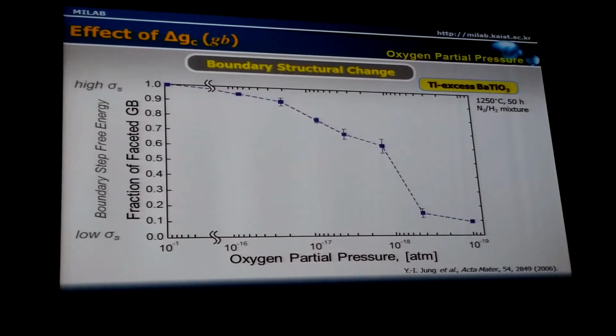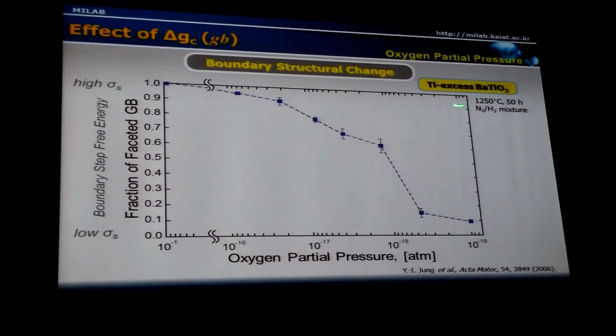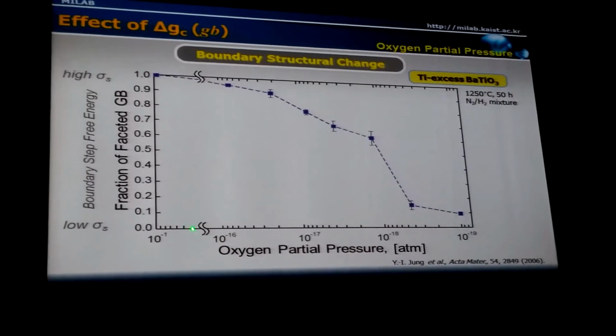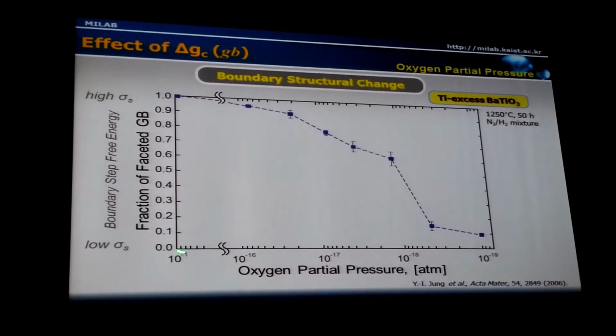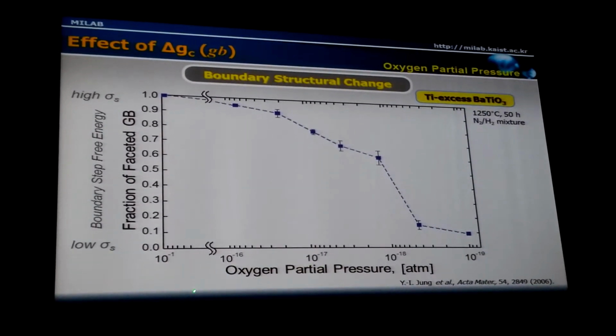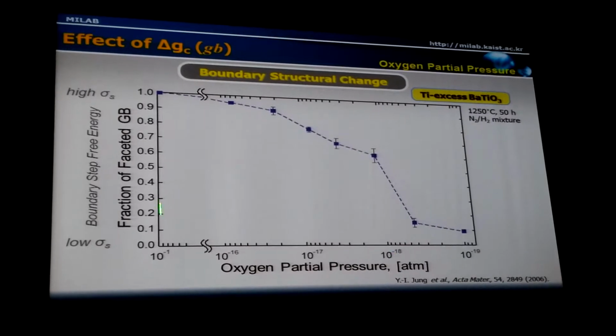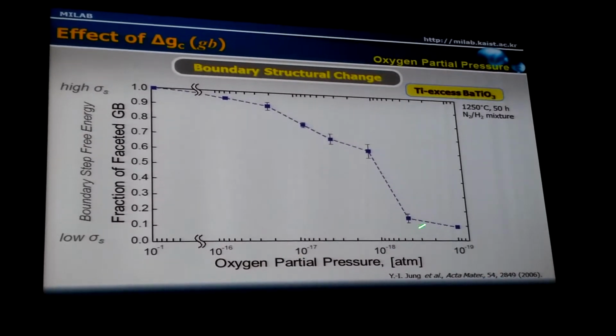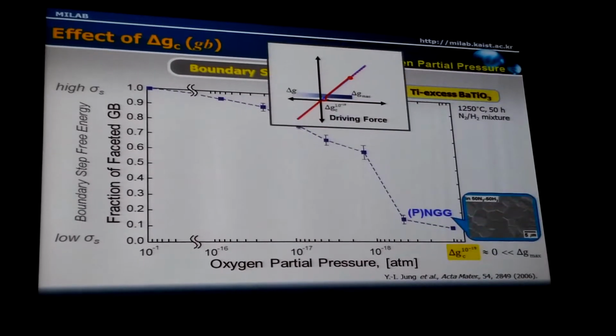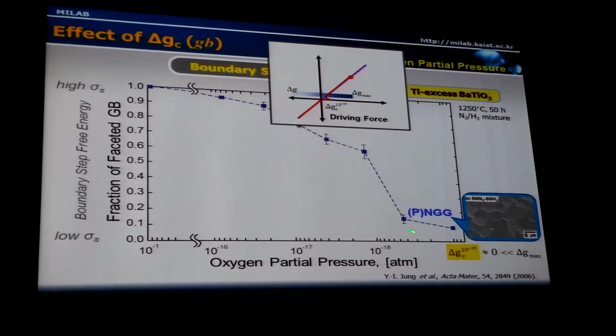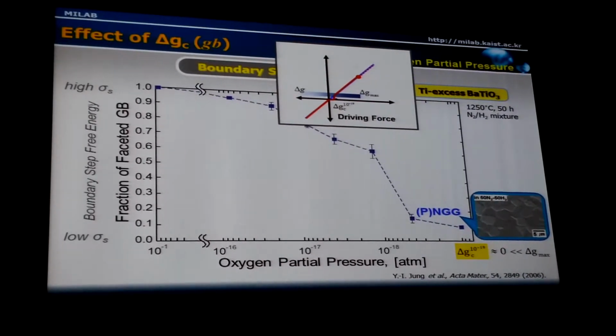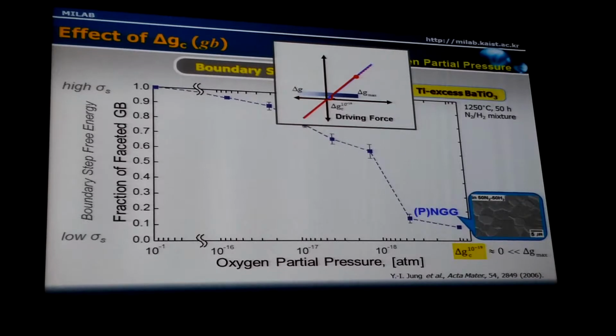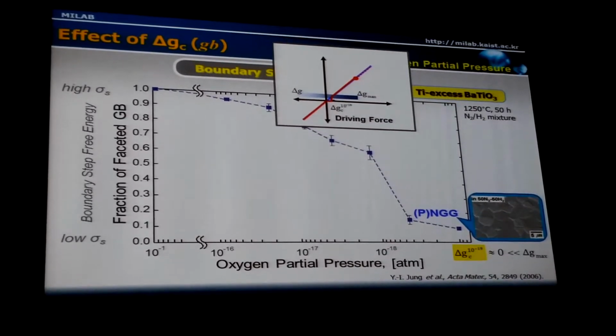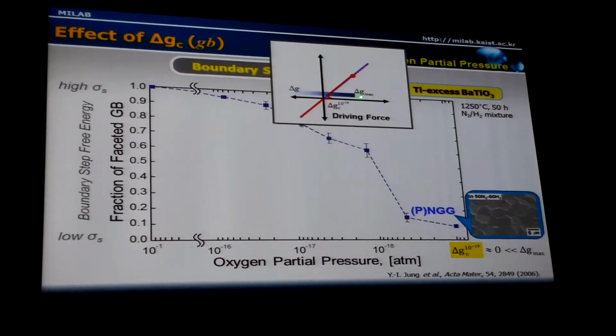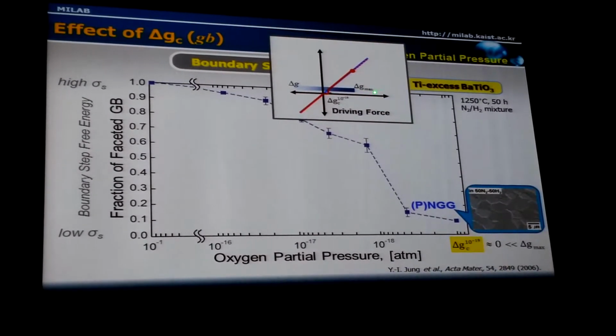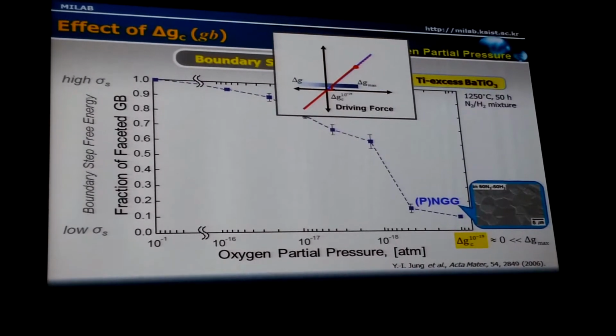We did a more precise experiment using the same material, barium titanate. This is a measured variation of fractional faceted boundaries as a function of oxygen partial pressure. As the oxygen partial pressure decreases, the fractional faceted boundary decreases. When we prepare samples at different oxygen partial pressures, in this case the grain growth is quite normal. That means most of the boundaries are rounded and rough, and normal grain growth is exhibited. This observation is related to the much larger maximum driving force compared with the small critical driving force.